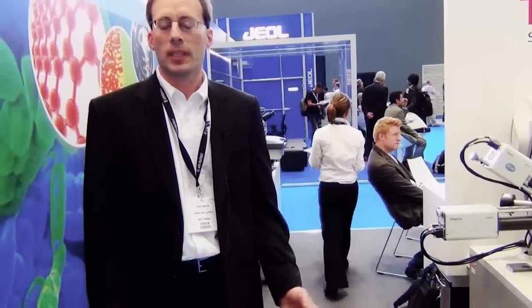We have two new products we're introducing at the show. One is a major advance in our EDS technology. We've taken our ultra-dry detector and improved the energy resolution, taking about 10 eV off of that historical energy resolution, down to 123 eV. And we've also introduced large area detectors.